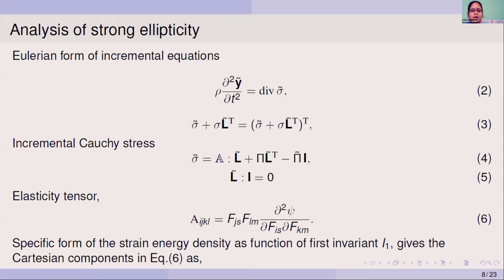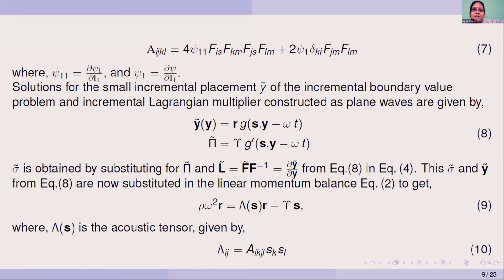So when this strain energy density psi is a function of only the first strain invariant I1, this elasticity tensor in its component form is as given by this equation 7. Here this psi11 and psi1 are the second and first derivatives of the strain energy psi with respect to the first strain invariant I1. This I1 is nothing but the trace of the left Cauchy strain tensor B, which is defined as F F transpose, where F is the deformation gradient.